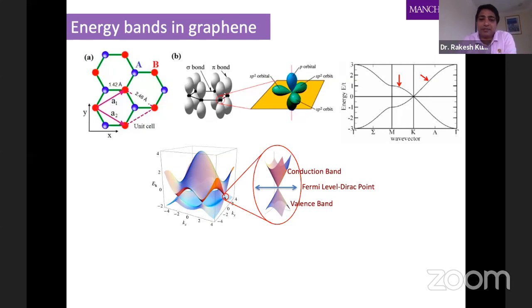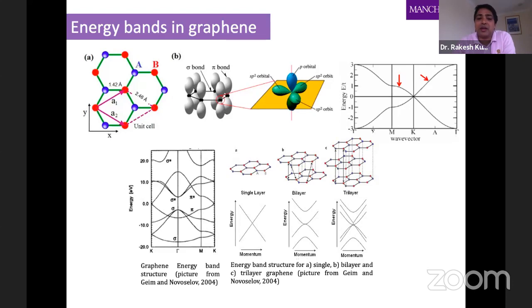large number of applications. So a single layer graphene has a very linear dispersion of energy at the Fermi level. But if you have a bilayer or trilayer, especially stacked, then it's possible to create a band gap also. So the research is still going on into how we can modify bilayer or trilayer in order to create a band gap. There are different routes. Either you functionalize the graphene flakes or graphene films to create a band gap, or you strain the graphene film in order to create the band gap. But still the research is going on to produce large scale graphene with the band gap so that we can use this material for electronics, especially for switching applications.